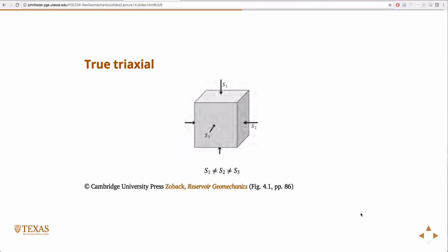Quartz is much stronger than clay. So samples for rocks have to be fairly large, much larger than what we need to assume a statistical distribution of material properties in a metal. If you were to test something like weathered granite, which is not the typical hydrocarbon-bearing sediment, you need a fairly large sample size. You might find yourself testing samples 3-4 inches in diameter with an L over D of 2. So it's a big sample.